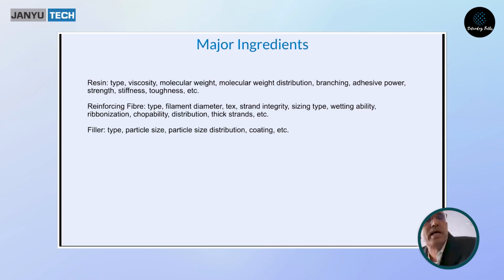When we are drawing the glass fiber in that diameter with enormous speed, it gets melted at 1650 to 1700 degrees centigrade. Then it gets filtered. Fiber drawing happens at nearly 1150 to 1200 degrees centigrade through a bushing made of platinum, gold, iridium metals. The bushing may have 2400 to 4800 small holes of that diameter, and immediately below that, it is generally an AC room. Fiber drawing is in an AC room.